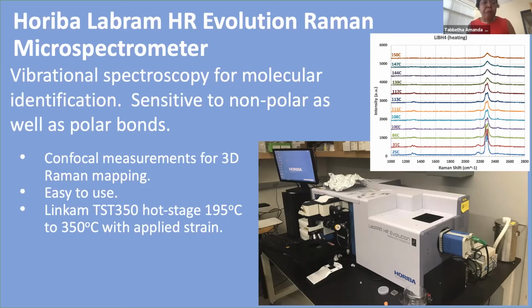And so for this instrument, it has confocal imaging. So that means that from the surface down to subsurface, by several micrometers, you're able to actually get your signal from the region that's in focus. So even if it's a subsurface in focus region, you're getting your spectroscopy from that region. And we're able to do mapping, X, Y, and Z mapping of your